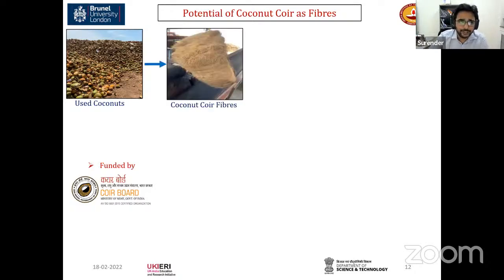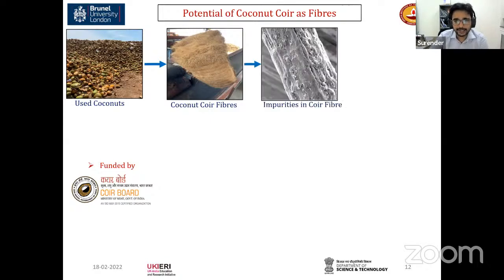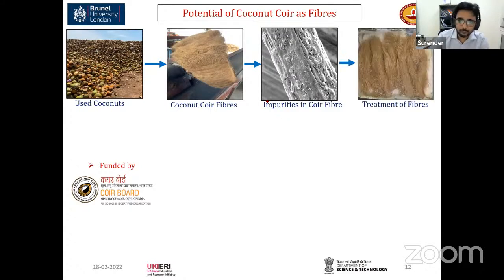So what we did, we tried to extract the fibers from this coconut, and what we found was a lot of impurities. First, it is very, very hygroscopic in nature. It has a lot of impurities. So we are working on developing strategies to improve the properties of this coir fiber, improving the tensile strength and the durability parameters. Now you might be thinking that this is biodegradable, right?